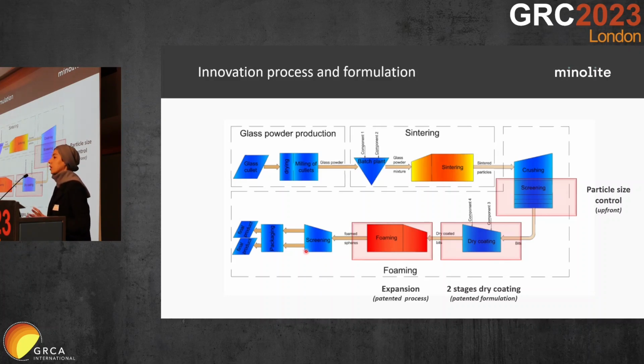So now we are comfortable with producing 4 different fraction sizes: 0.5 to 1 millimeter, 1 to 2, 2 to 4, and 4 to 8 millimeter. But we are also working on optimizing the parameters for production of particles less than 0.5 millimeter, and also larger particles, 16 to 30 millimeter.